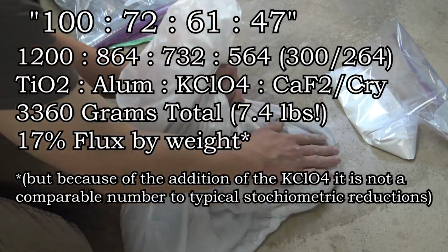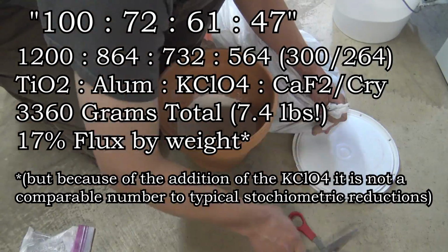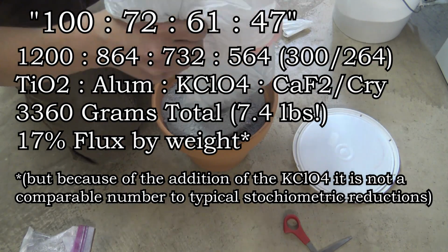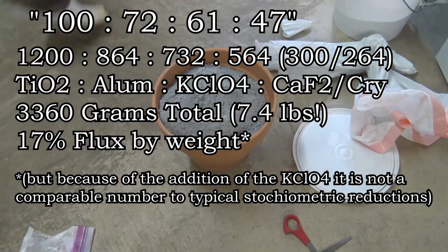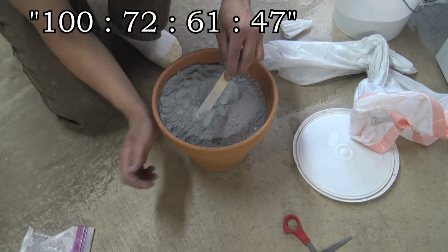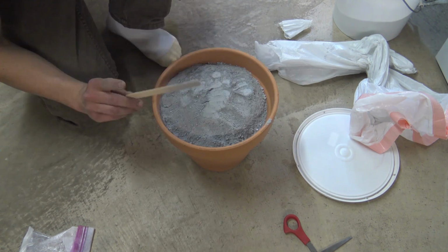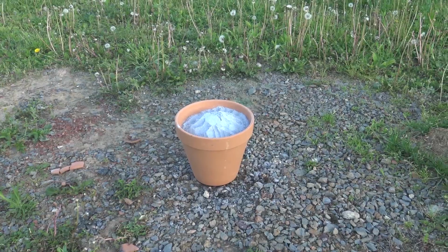Care must be taken to remove all lumps from ingredients prior to mixing, and make sure the aluminum is mixed in with the oxide and flux before the perchlorate is mixed in. Ziploc bags didn't quite cut it for this one, so I had to mix it with a garbage bag. Well, let's take it outside and get very far away.